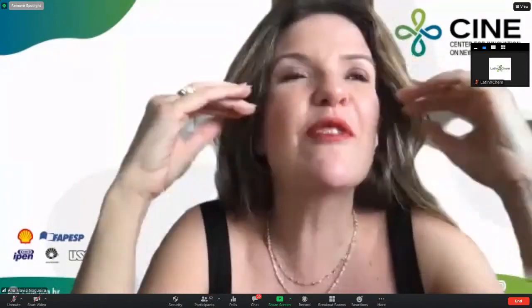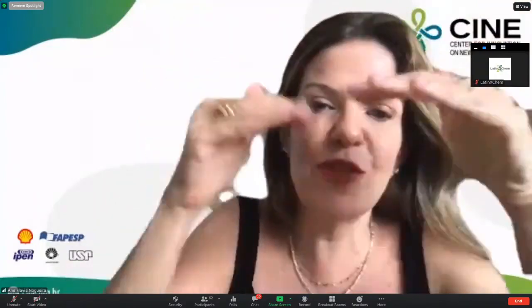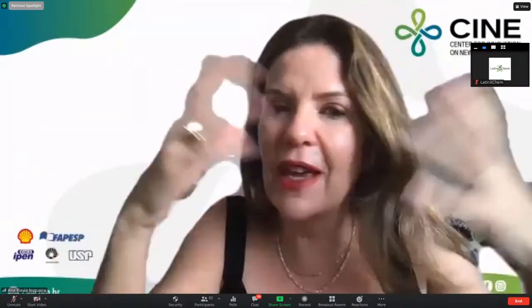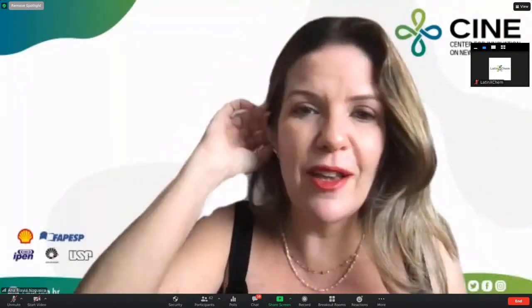We are now trying to understand what is actually forming, because with the temperature we don't see the peaks of this 2D structure anymore. But believe it or not, the devices are even more efficient, even after such kind of degradation. So the 2D is probably transforming into a mixed phase that is improving the stability. We are very anxious to start, because the synchrotron was shut for more than a year. So I hope that soon, next year, we can start to do these in situ experiments again. Awesome, thank you.